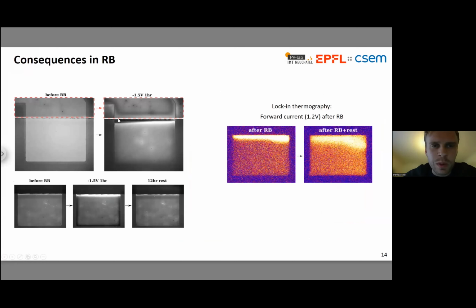So often when we reverse bias our devices, we see pictures like the following. Now I'm showing you the full device rather than just a zoom. So we have activity at most of the boundaries. You can see, this device before and after reverse bias, we've got darkening at the ITO boundary. We've got something happening at the silver boundary, although it's not as noticeable. And that's in PL. And when we look then at current flow, on the right-hand side, I'm showing the same type of device after reverse bias, and then a little while afterwards, after it's rested. We see this enhancement of forward current passing in the region where there are these patterns of ion migration. So it seems pretty clear that the laterally migrating ions are affecting the current voltage properties of your device.